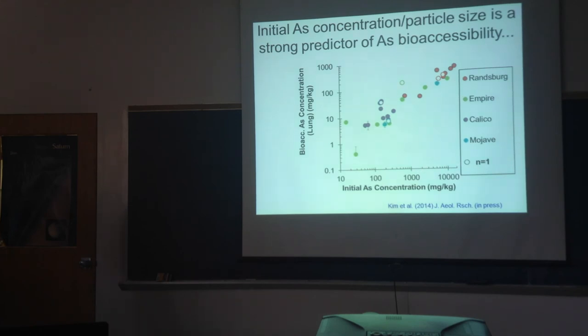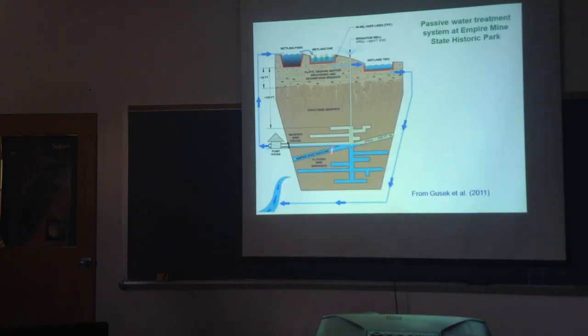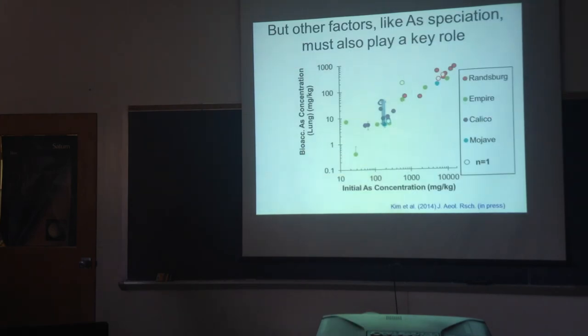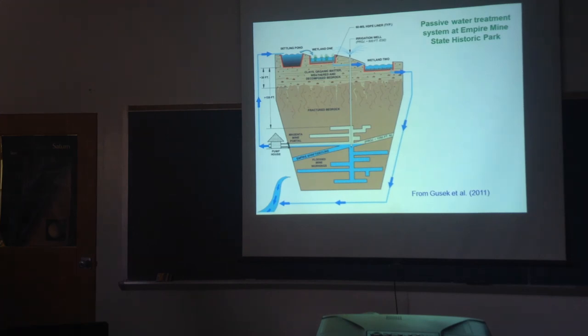He actually uses a lung leach. I mentioned gastric leach, which simulates stomach fluid at pH of 1.9, 37 degrees C, body temperature, and so forth. There's a different leach test that we do to simulate what's going on in the lung. There are actually two different types of fluids in the lung, a neutral one and a more acidic one when the white blood cells attack invading particles. And so both of those are important to do. In this case, I believe he's looking at the more neutral lung leach. Okay. So I better wrap things up.